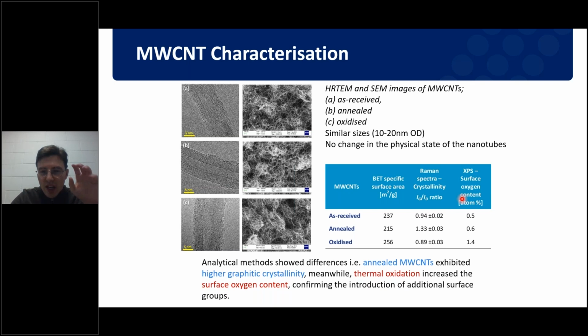Then to this same sample, we have annealed these carbon nanotubes. So this was heated to above 1000 degrees Kelvin for an extended period of time to see how this is going to influence its dispersive surface energy and its polar surface energy. And we can confirm that the annealing has had an effect on the structure by looking at its Raman crystallinity. So we can notice the influence that that high temperature annealing is having on the structure.